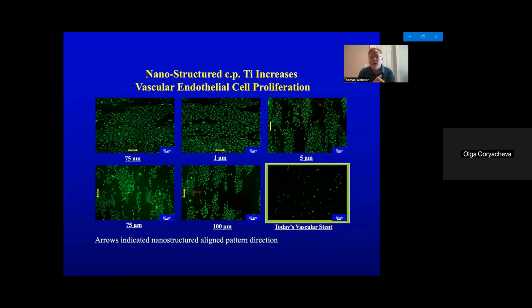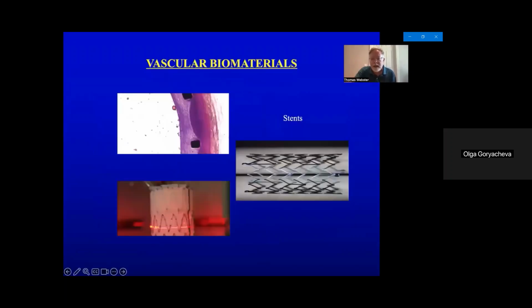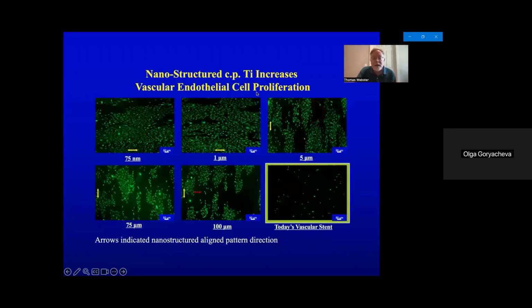Don't change the chemistry. You don't have to change the implant procedure. All you're doing is taking the same stent that has been commercialized and used for decades and create a nanotexture that can reduce chances of thrombus and inflammation and increase the embedding of that stent into the vessel wall to prop it and keep it open. And keep in mind, all of these things that I am mentioning were done without drug release. One of the big problems with stents about 15, 20 years ago were drug-eluting stents, where companies were putting drugs in stents, but unfortunately, some of those drugs that were released were not released correctly and led to patient death.